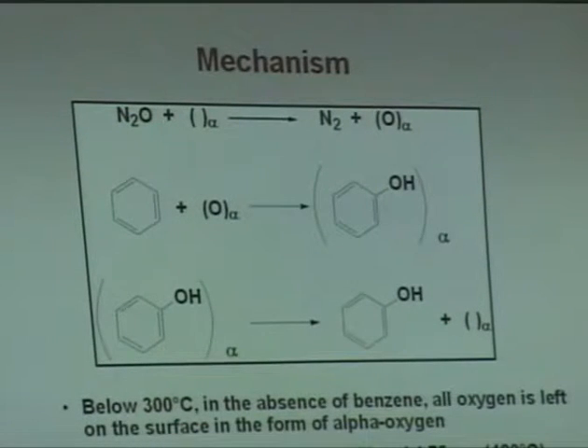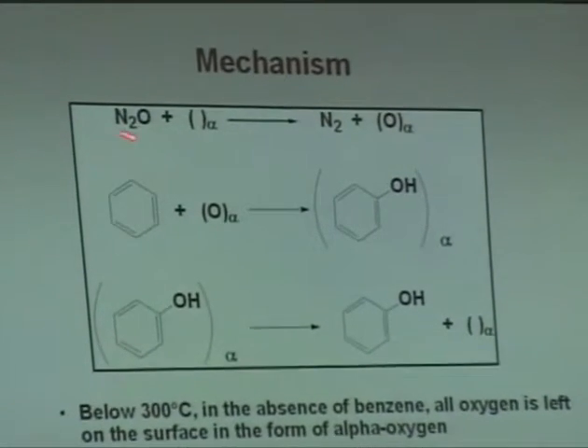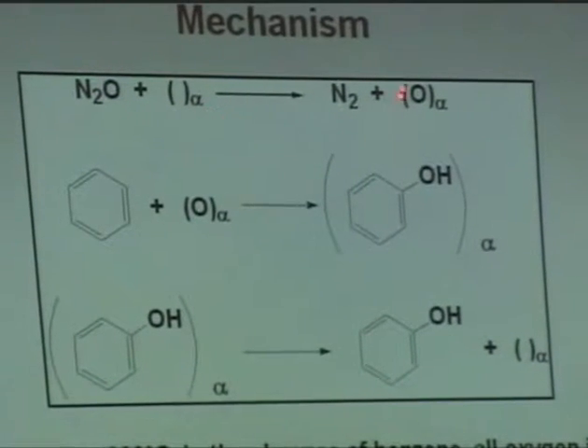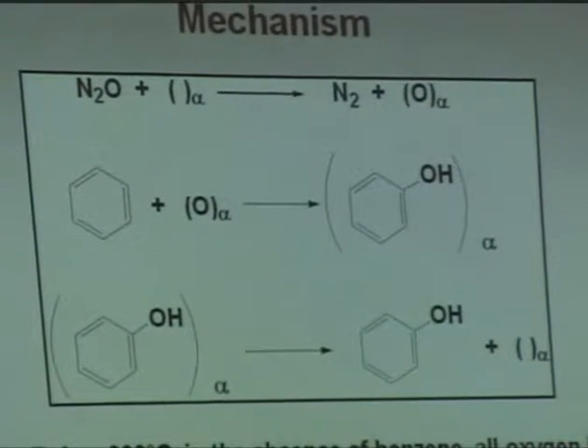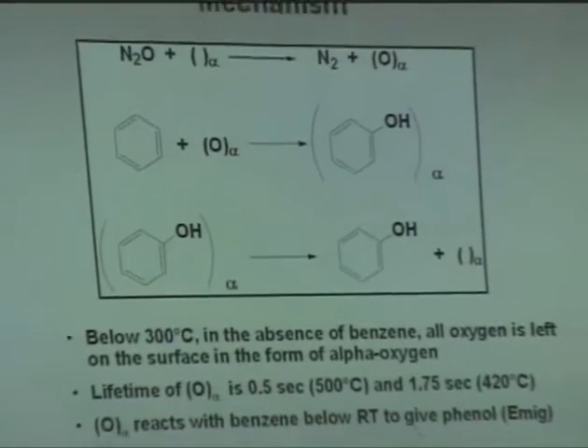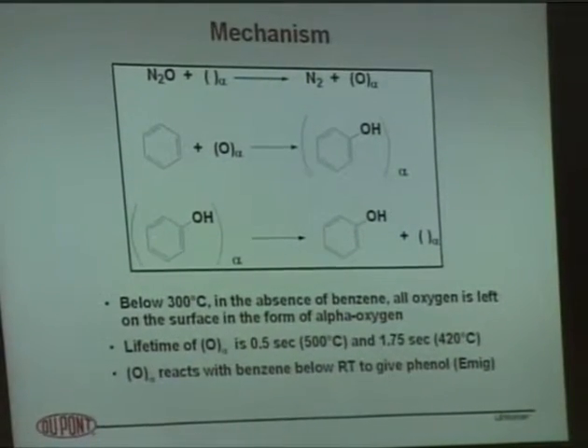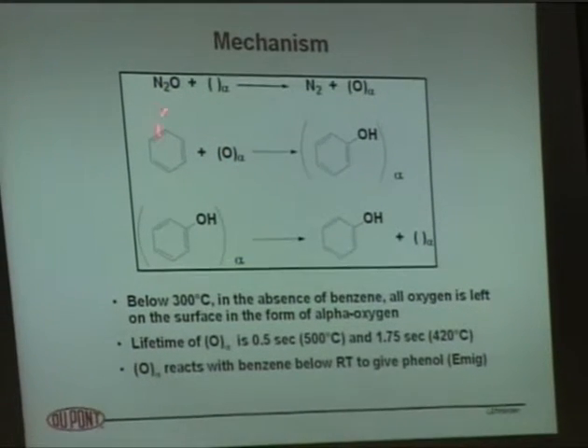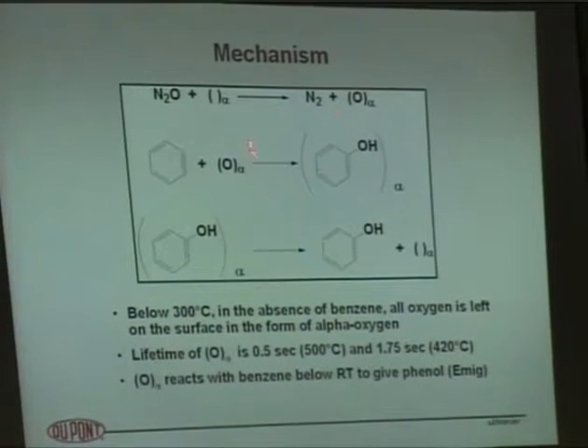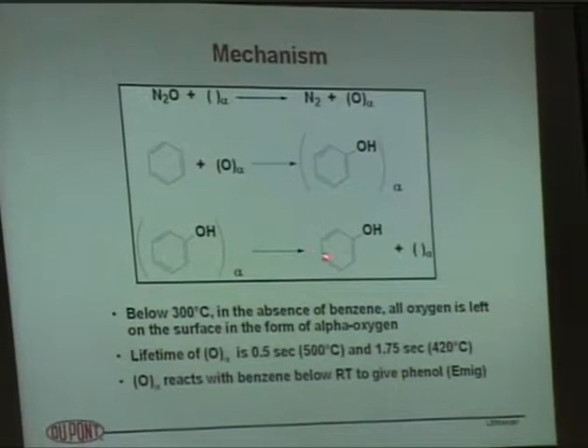But the mechanism is very interesting. They're proposing there are these alpha sites on the catalyst surface. The N2O sits down on the surface of the catalyst, decomposes to give nitrogen, and this alpha oxygen site on the surface that's very, very stable. This oxygen on the surface then reacts with benzene to give phenol that is desorbed to regenerate this vacant alpha site, which can react with more N2O.